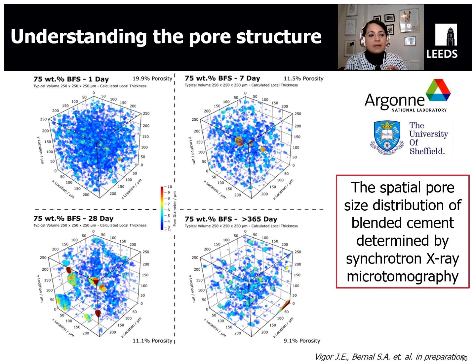Because one of the most challenging things when studying cementitious materials is getting a realistic overview of the pore structure. A lot of the testing methodologies that we use require preconditioning that might induce microcracks in the materials, or we cannot visualize how the pores actually distribute. But this technique is non-destructive, is very powerful, and enables us to see pore size distribution, tortuosity, and therefore calculate diffusivity of cementitious binders.